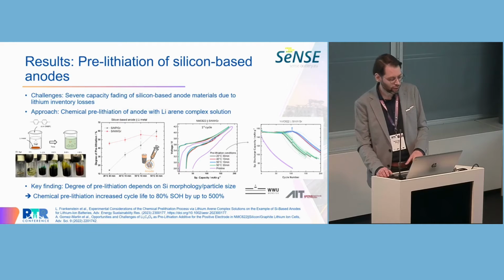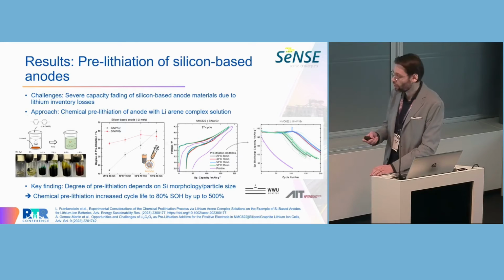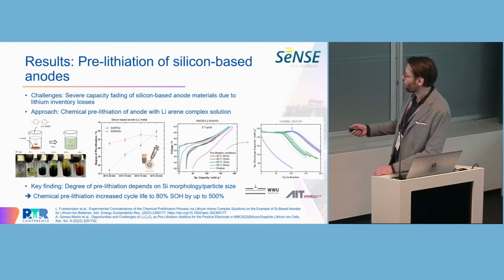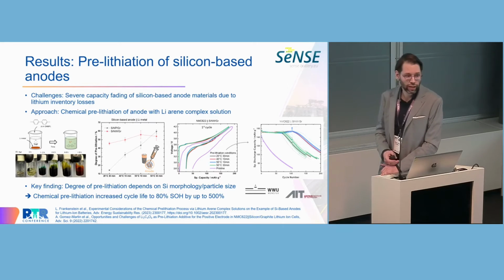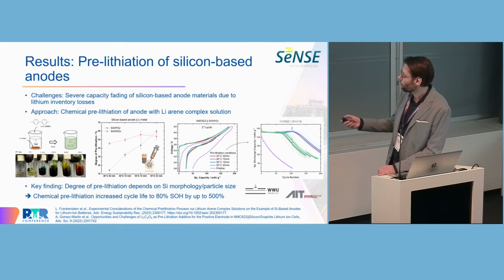and pre-lithiated the material. In that way, you form a kind of reservoir of lithium, and you can then really nicely extend the cycle life. You can see here on the right side in purple, the cell without any pre-lithiation showed really rapid capacity fading, but with the pre-lithiation we could achieve a stable capacity here for more than 100 cycles.